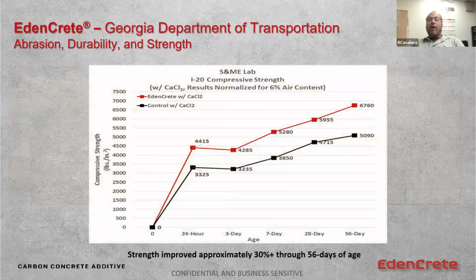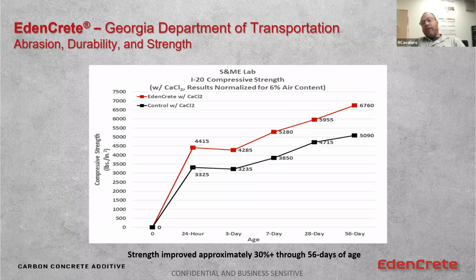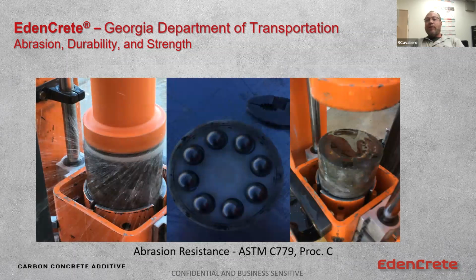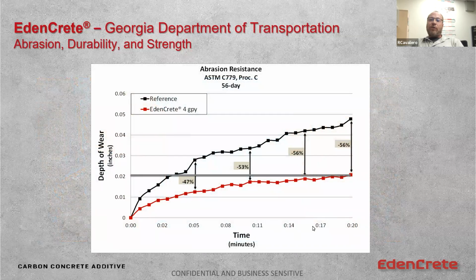We also did lab testing in parallel, and we saw that the EdenCrete had actually improved the compressive strength about 30% across all ages. We wanted to demonstrate to them how much it improved the abrasion resistance. And so we ran a test where you take a concrete cylinder shown here on the right, and you take these steel ball bearings, which are facing the ground, and you push them into that concrete, and they spin at 1100 RPM with a 27-pound force. And there's water used to help the abrasion. And you plot the depth of abrasion versus time. It's a 20-minute test, shown on the x-axis, the depth of abrasion shown on the y. And we see that EdenCrete in the red achieved a depth of abrasion 50% better than what the reference achieved.